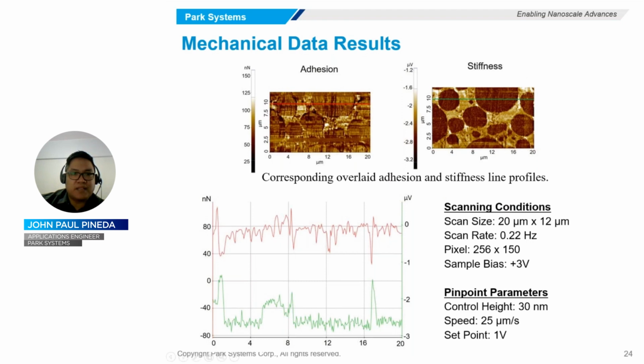And then lastly, here are the mechanical data results we have acquired in the experiment. The adhesion image doesn't show significant variation between the plateaus, and a tendency towards higher adhesion is observed between the plateaus. In the stiffness images, the brighter areas represent a surface with lower stiffness, while the darker areas correspond to the surface with higher stiffness. The stiffness image here shows noticeable stiffness variation in the sample surface.